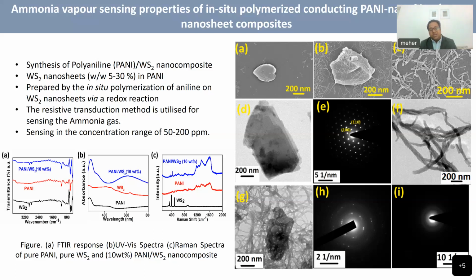We prepared these two-dimensional tungsten disulfide materials by the lithium intercalation method. We know that we have layered materials like tungsten disulfide, and we want to peel off the layers one by one. In the lithium intercalation method, lithium goes inside the layers, and then we peel the layers with the help of lithium. So chemically we synthesize tungsten disulfide, and chemically we also synthesize polyaniline nanofibers. And in the process of making the nanofibers, we embedded these tungsten disulfide nanoflakes in the fibers.